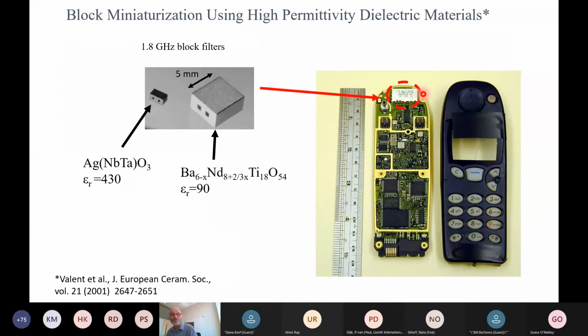Just an example, sort of old school, but just to give you an idea of a very old phone setup. Obviously, these are replaced by bulk acoustic wave sort of devices, but it's good to use this as an example of why high permittivity was important. And this block filter, we were working on different materials, basically to increase the permittivity of this existing material from 90 to 430 while keeping the temperature coefficient also low, and also the loss very low. And just by going from 90 to 430, we could then miniaturize this quite a bit.